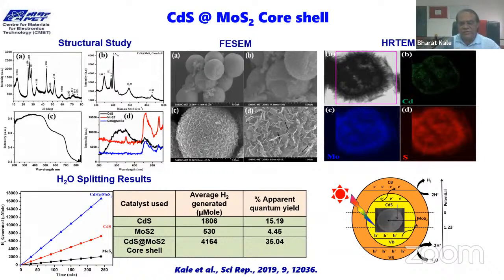Then we have MoS2 already with us, and then whether we can make a core shell. So MoS2 in the core and CdS in the shell side, so that there is sensitization through the CdS and the electronic phenomena, or hole recombination and electron transport, through the MoS2, whether it is possible. So we did that, and we found that core shell structures can also give good photocatalytic activity.